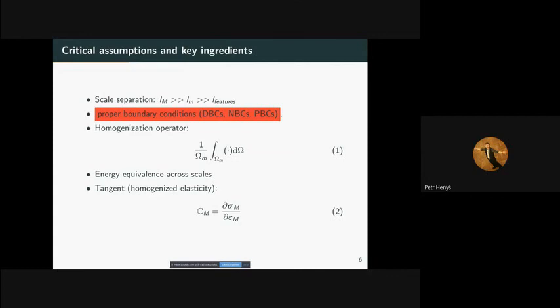So once we trust our scale separation, we should use proper boundary conditions, right? We can basically use 3 types of boundary conditions, very usual ones: Dirichlet, Neumann, and also the periodic, which are most interesting for multi-scale coupling and homogenization. Once you set the boundary conditions, you also need to be able to compute the volume integral of the quantities of interest. For example, if you want to know the elastic tensor, we can take our stress tensor, do some temporal and spatial averaging with that integral, and then we get what we call the effective stress tensor, right?